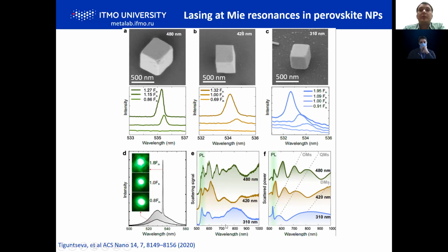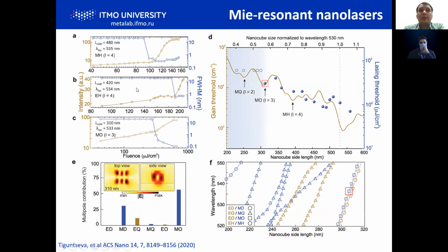Scattering experiments showed that the smallest nanocubes supporting lasing, which is just 310 nanometers in size, with lasing around 530 nanometers, as you can see here, support Mie resonances around the emission wavelengths. We also performed all laser characterization for these nanoparticles and observed a dominance of the third-order Mie mode for these nanocubes. This is the domination of the magnetic octopole for this particle. And this is a map for different nanocuboids in comparison with theory. So we see that the laser threshold needs a gain of around 10,000 in material gain.